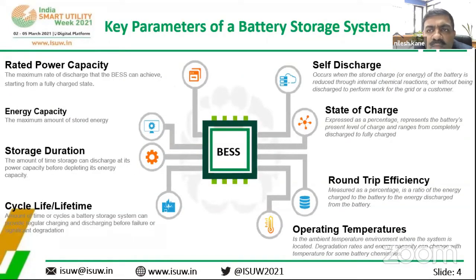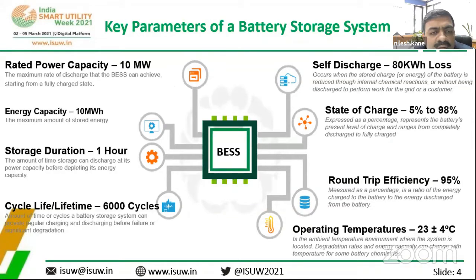So these are the key parameters of the battery storage for the last 2 years. We are monitoring, obviously, the rated power capacity, the energy capacity, and the storage duration is very important. The cycle life and lifetime: we started with 1 cycle a day, and during the summer season, we have gone up to 1.5 cycles per day. So the self-discharge, state of charge, regular temperature monitoring, and regular monitoring of round trip efficiency. In the last 2 years, we have measured round trip efficiency and DC to DC efficiency as an important parameter every year. Next point.